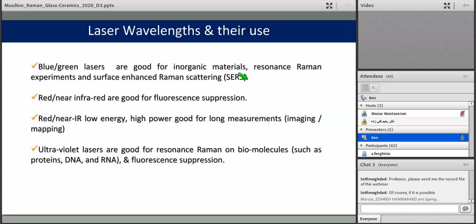Red and near infrared lasers are excellent for fluorescence suppression. They're also good because of their low intensity. They don't tend to damage fragile samples. So when you're making an image or map, like I showed at the beginning, you can use these wavelengths so that you ensure that there's no damage and you're getting actually the vibrations of the material, not the damaged material.